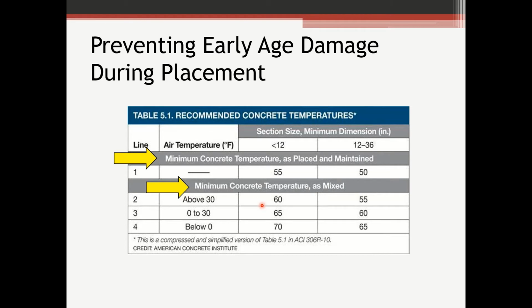These next three lines, 2, 3, and 4, these are the minimum concrete temperatures as mixed. So if your ambient air temperature is above 30 degrees, again, we're still in a cold weather situation, minimum concrete temperature is 60 degrees. If it's 0 to 30, 65 degrees. Below 0, you want that concrete temperature to be 70 degrees.